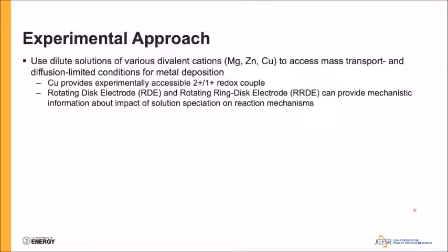So the approach that we're taking in this work is to move away from looking at just bulk plating and stripping response and move towards dilute solutions of the working divalent cations. We do this in order to access both mass transport and diffusion limited conditions for metal deposition and start to evaluate more of the mechanistics of the processes themselves. I've thrown copper into the mix in the study specifically because you have an experimentally accessible 2+/1+ redox couple. So we can start to get some idea of what the electrochemical response of the 2+/1+ redox event actually looks like in these non-aqueous multivalent electrolytes.